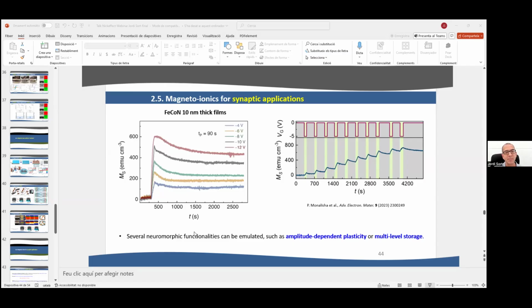The reversibility depends on the applied voltage. So if you apply too much voltage, like for example -50 volts, you will induce a lot of effect, and then even if you apply positive voltage, you will just reverse the material partially. So we want to have good cyclability or reversibility. We need to stick to relatively small changes of magnetization, and then you can modulate it reversibly.